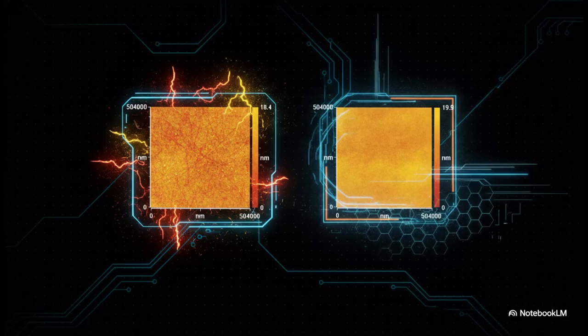The visual proof of this filtration mastery is honestly just stunning. Take a look at the difference here. A copper wafer polished with an unfiltered slurry gets absolutely decimated by microscratches and pits from those agglomerated particles. But a wafer polished with properly filtered slurry, using multi-zone graded porosity media, shows this remarkably smooth, nearly defect-free surface. I mean, we are literally looking at the difference between a functioning microprocessor and a completely useless piece of silicon.